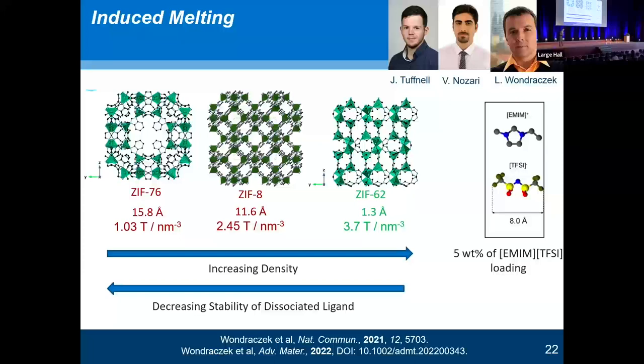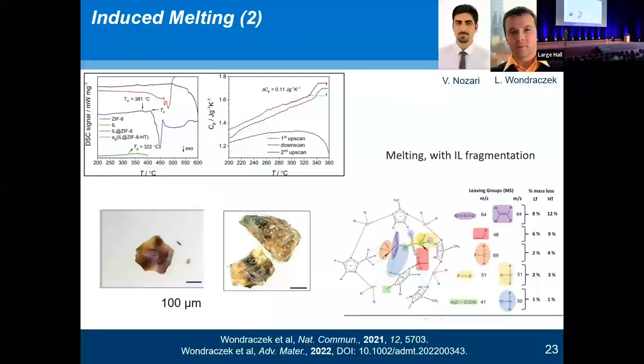Well, the idea is that we artificially increase the density by loading them with an ionic liquid, ethyl methyl imidazolium bis(trifluoromethylsulfonyl)imide. I've not made life easy for myself this morning with some of these names. Anyway, we load it with an ionic liquid and look at the stability of this dissociated ligand, how it changes when there's something else in your pore. And in our case, it works a treat. From a non-melting system, now we can make beautiful glasses from ZIF-8 and higher order systems.